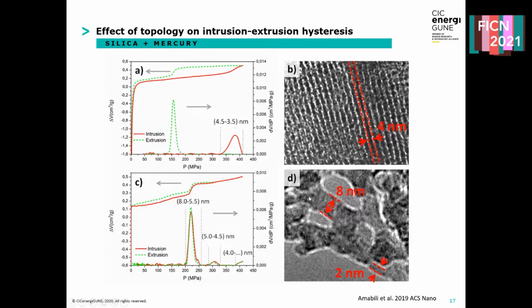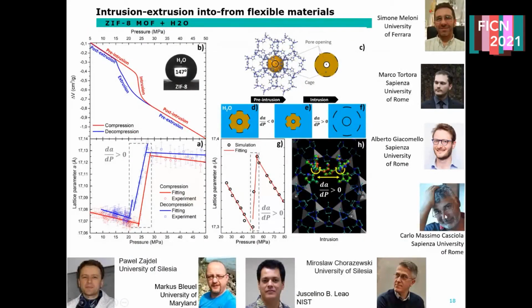But once we use disordered pores, which provide a lot of small pore sites for the bubble nucleation, we actually saw almost no hysteresis in the intrusion-extrusion cycle. So this is quite promising in terms of generalizing this concept for liquids other than water.